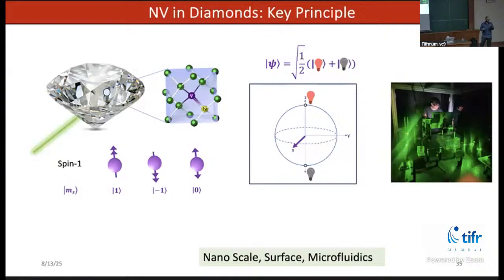With a very simple setup, one can shine an LED, and the electron spins in the diamond would be highly polarized. But there is a problem, and that problem is the polarization does not come out of the crystal. So if one brings a protein on top of the diamond surface, the protein is not hyperpolarized. The small organic molecule will not be hyperpolarized. I'm not too much into diamonds, but those who have studied diamond say the surface of diamond is not clean. There are a lot of dangling bonds, and that causes fast decoherence on the surface, although inside the coherence time is very long.